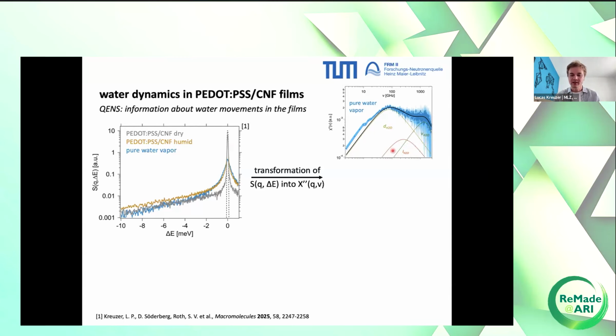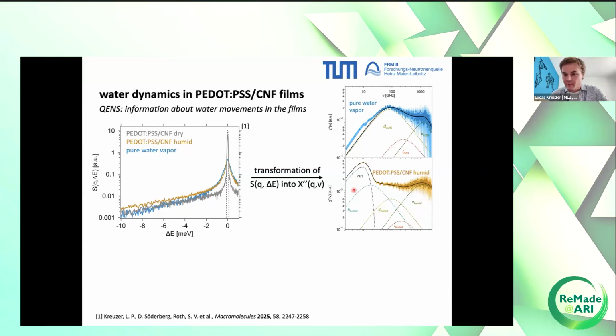So this is only pure water, and if you now put this water molecule into a polymer film, the situation gets even more complex. Namely, it's this graph, this curve here. So again, we see these three contributions: the diffusion, this effective local motions, and the vibrations. But we have two more peaks coming up. A very prominent peak at very low frequencies, meaning very, very slow movements. And these are all the movements that come from the polymer side chains, backbone movements, and so on.